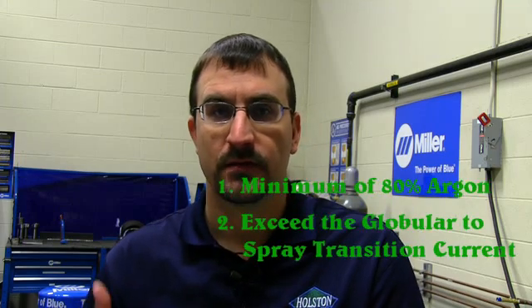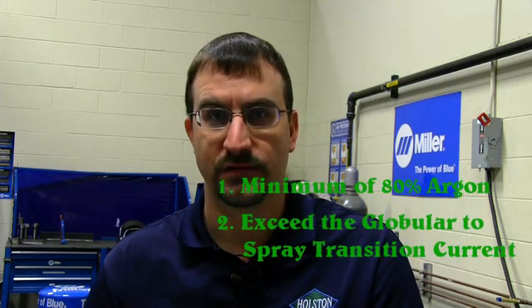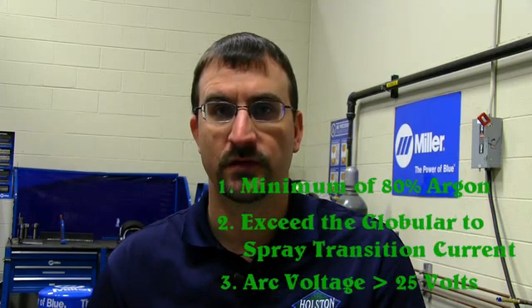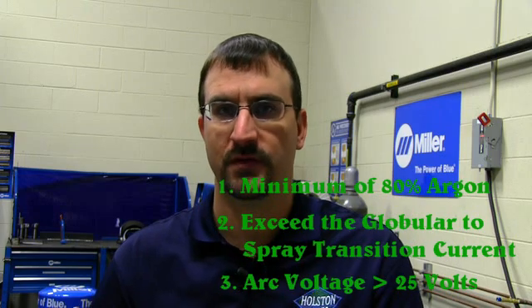So the three things that are necessary to be in a spray transfer are 80% argon, to exceed the globular to spray transition current, and to have a voltage of at least 25 volts for most applications. Most of the time, it's going to be slightly higher than that, but 25 volts is a good starting point. And once you have these three conditions met, you should be able to get into a spray transfer.